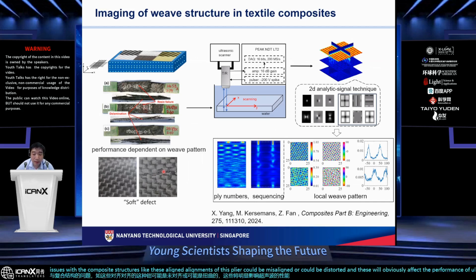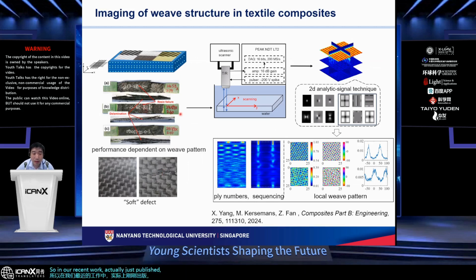So in our recent work, which was just published this year, we are trying to use ultrasound to reconstruct the ply information along the thickness. We are using ultrasound together with 2D analytic signal techniques. We are able to extract not only the phase information, but also the frequency information. We are able to get the ply alignment at different locations. So that's something we did quite recently.